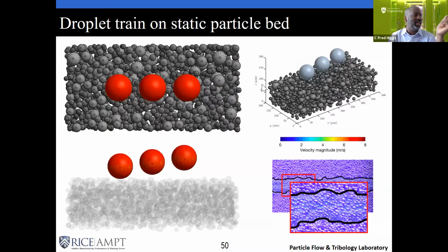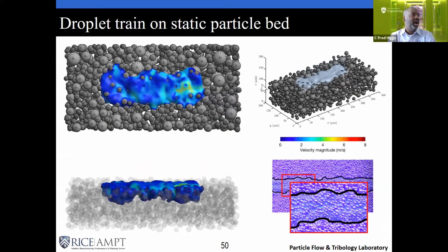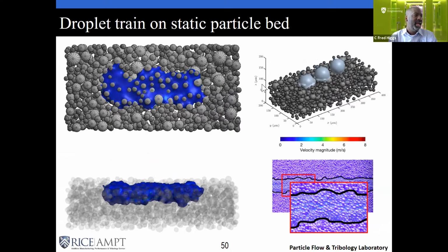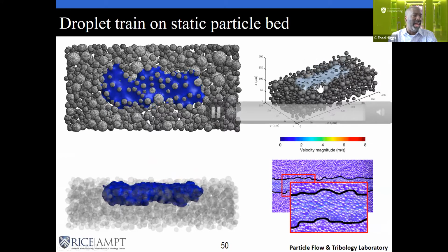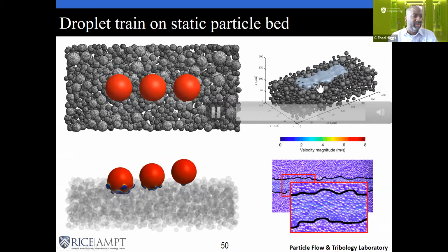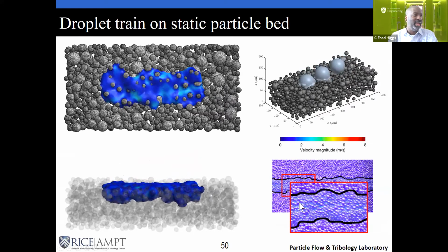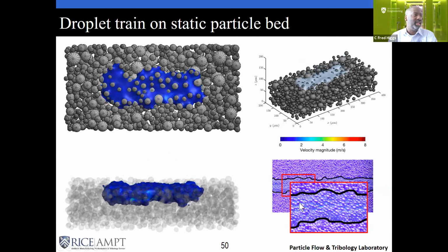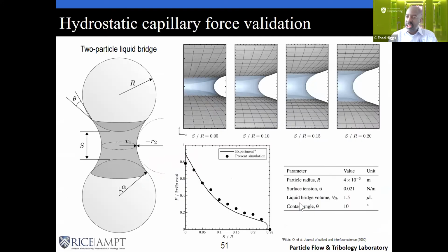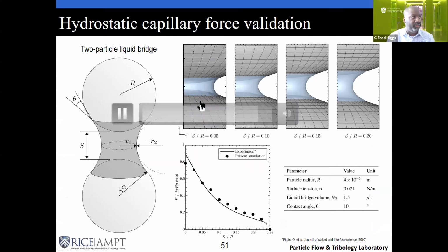So then we said, well, let's look at it if multiple droplets are hitting a powder bed. And we thought that looked similar to what we've observed there. And so we said, then let's start to relax things. The first thing we do is look at validating this. Here we looked at what was in the literature. Someone had two particles and a liquid film separating them, and so you have different separation distances.